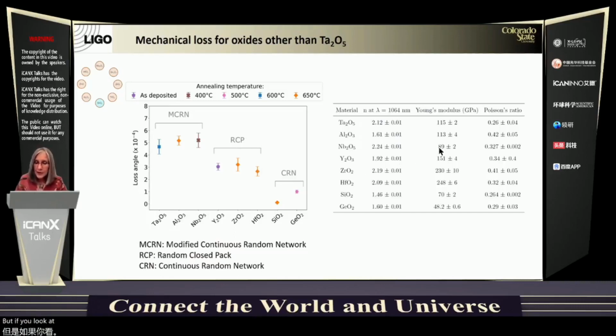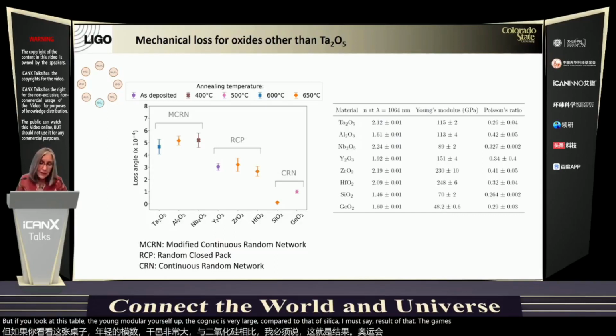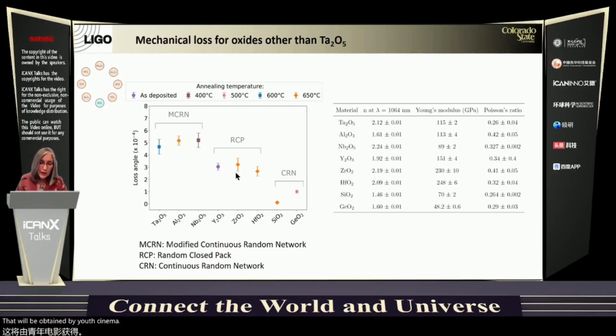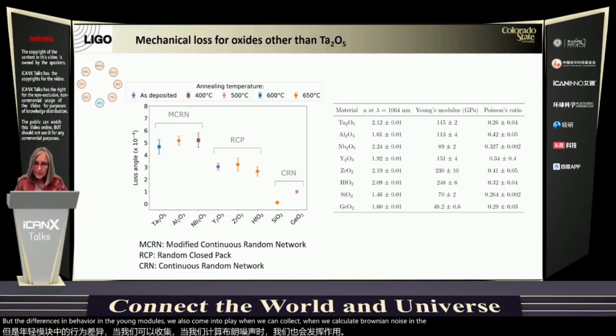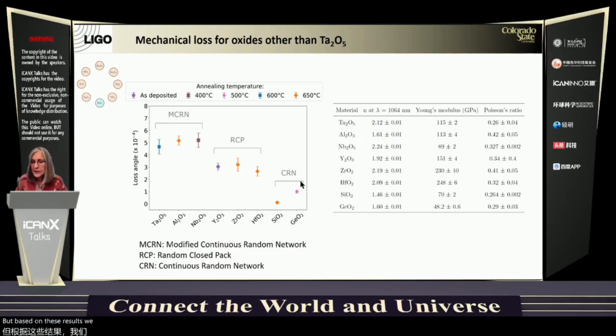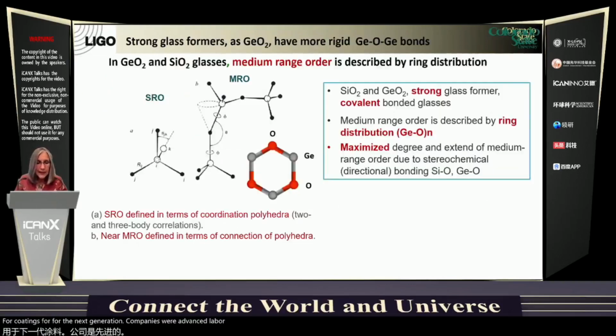But if you look at this table, the Young's modulus of zirconia is very large compared to that of silica. And as a result, the gains that would be obtained by using a material with lower mechanical loss angle will be offset by the differences in the Young's modulus, which also come into play when we calculate Brownian noise in the coatings. But based on these results, we decided to investigate whether germania would be a good candidate as a base for the next generation coatings for Advanced LIGO Plus.